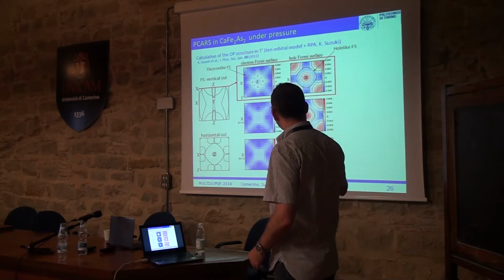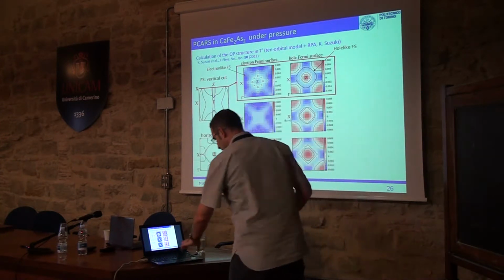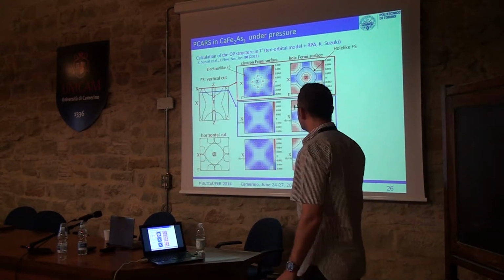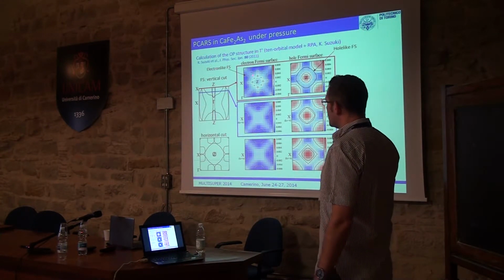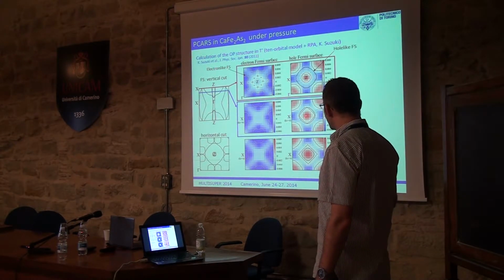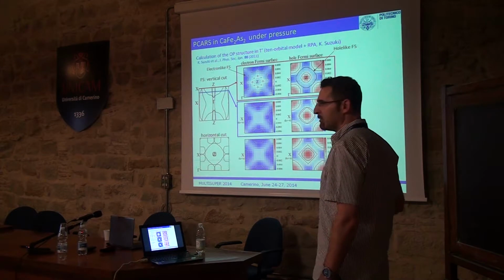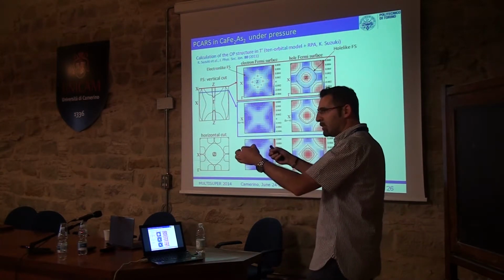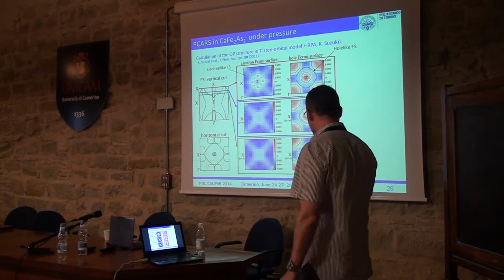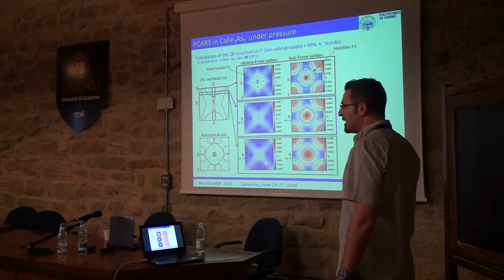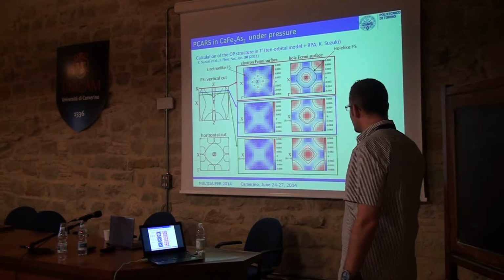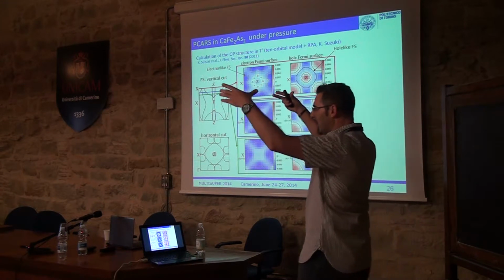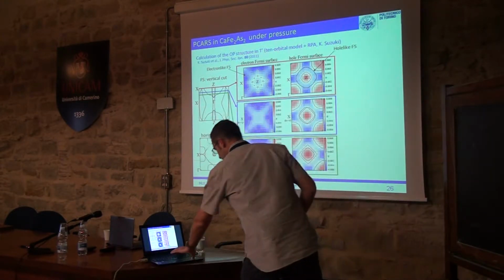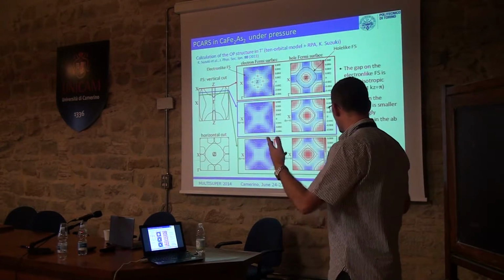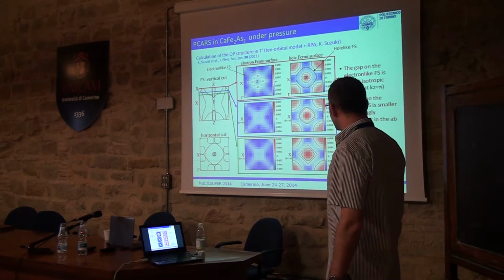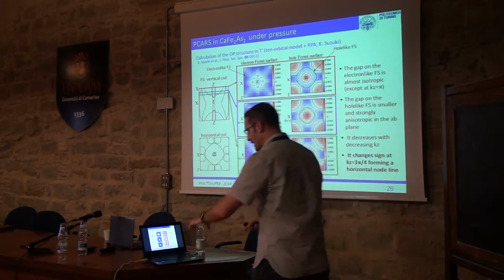The lines of nodes are the red lines that lie far apart from the Fermi surface. In the second cut, here, we have an almost isotropic gap on the electron-like Fermi surface, but on the hole-like Fermi surface, the line of nodes is touching the Fermi surface. So here we have nodes that touch the Fermi surface. And in the third cut, again, same thing, almost isotropic gap here, and here the gap has completely changed sign. So we have a line of nodes at kz equal to about 3 pi over 4, and here we have almost a horizontal line of nodes.